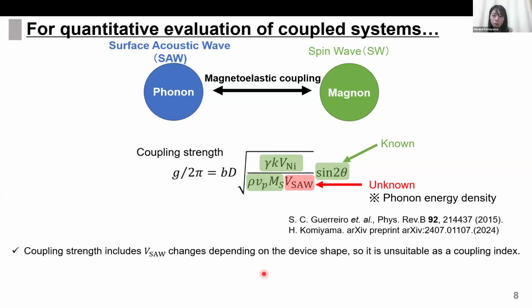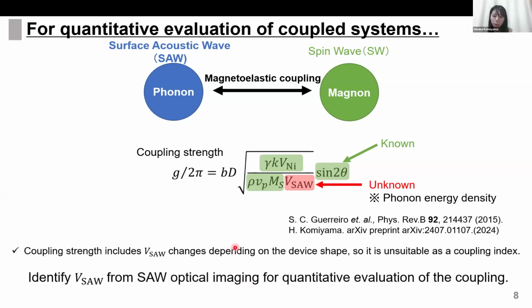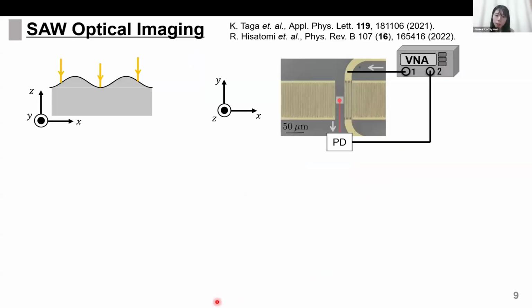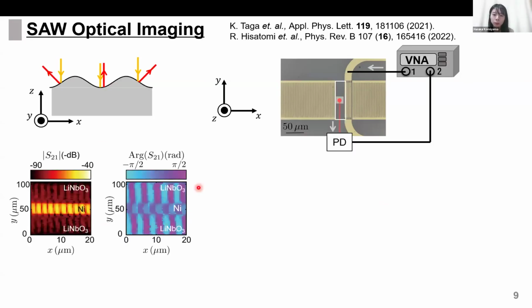For quantitative evaluation of the coupling, we identify VSAW from optical imaging of surface acoustic waves. The spatial distribution of surface acoustic wave was obtained by observing the modulation of the reflected light path according to the surface tilt using the photodiode and VNA. First, I show the amplitude and phase map of the signal scanned within this white frame.